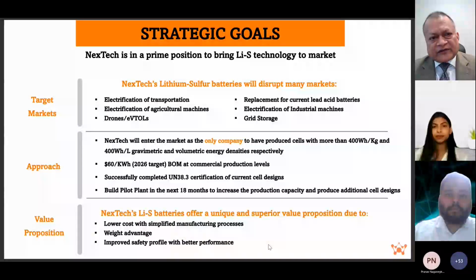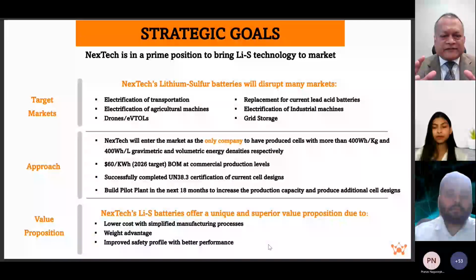With regards to lithium sulfur, the cell voltage of lithium sulfur is identical to that of a lead acid battery cell voltage, 2.1 volt. That means I can put 6 cells in series and you have a lead acid battery replacement. But the size will go down by 50 to 60%, and the weight will go down by 70%. Imagine that. And obviously electrification of industrial machines and for grid storage.